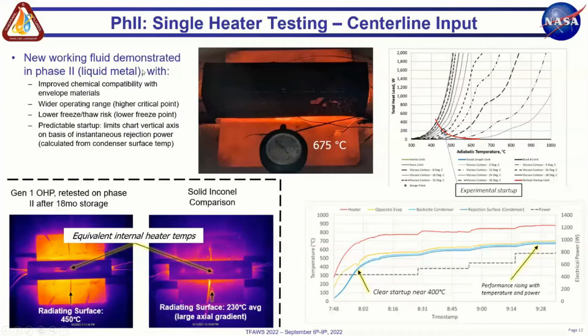We pivoted to using a different working fluid, which is liquid metal. We have improved chemical compatibility with the envelope materials of interest, superalloys, wider operating range than the fluid shown in phase 1, higher critical point and lower freezing point, both valuable. And again, with this new working fluid, we've been able to experimentally demonstrate a predictable startup in relation to the OHP limits of operation.